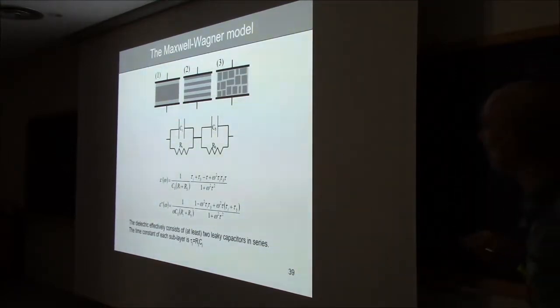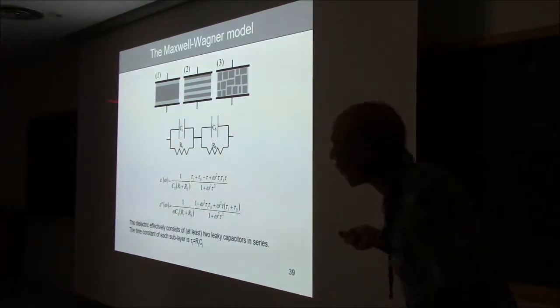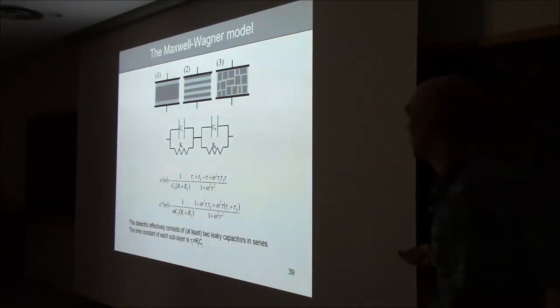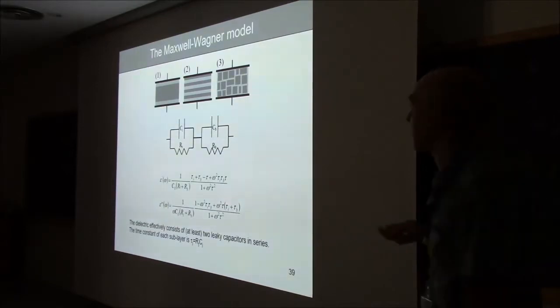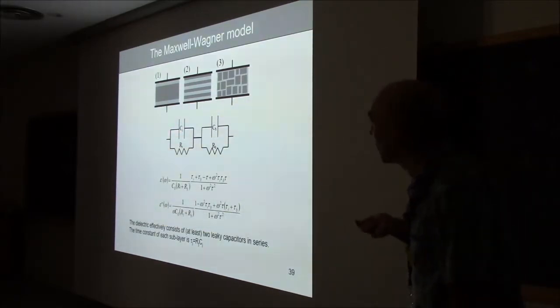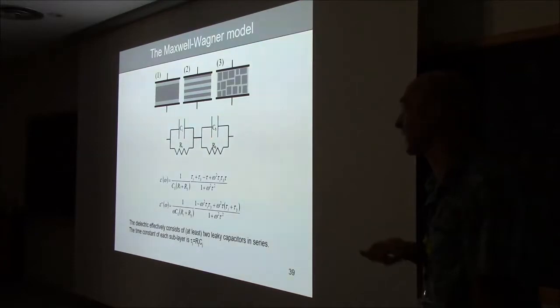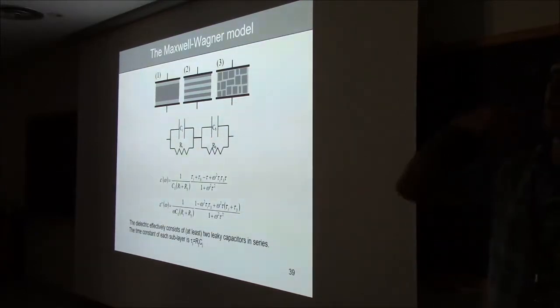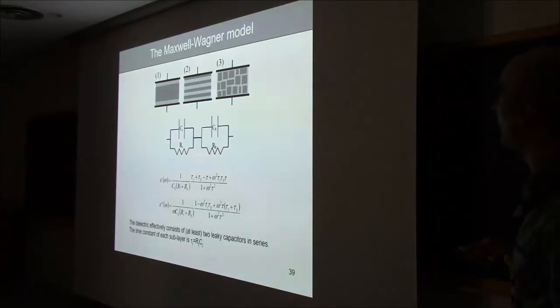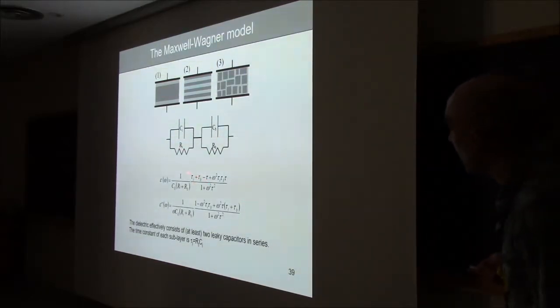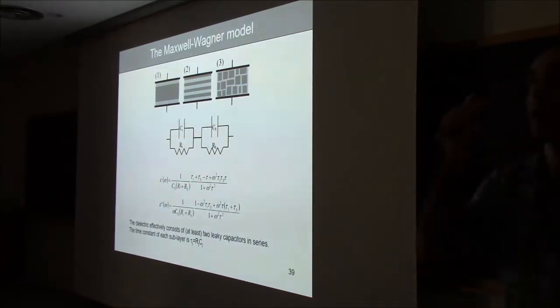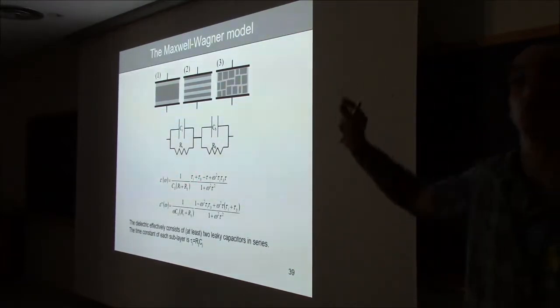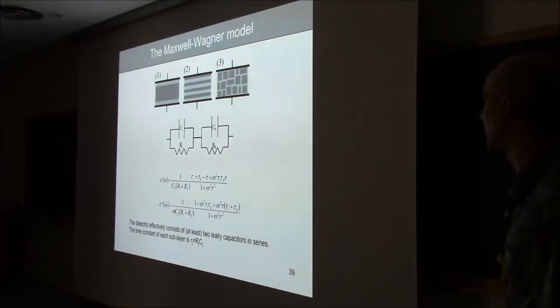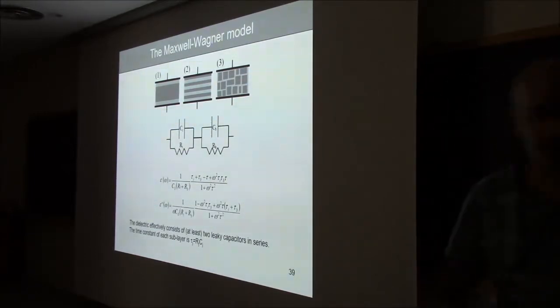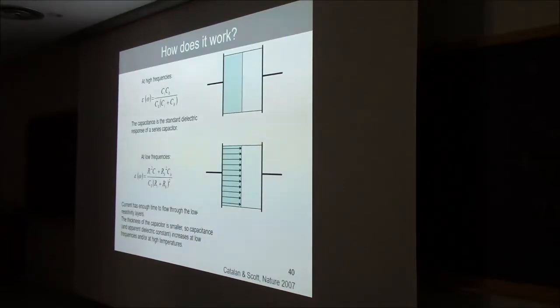The simplest way to model this two-component leaky dielectric is by what's called the Maxwell-Wagner circuit. These two leaky or lossy capacitors in series with each other. If you calculate the dielectric impedance of this circuit, this is just an equivalent circuit model, you will see that it depends on these taus. Taus basically are the resistance times capacitance time constant of the two elements. Okay. This looks like a very complicated equation, but the physics is actually much simpler.